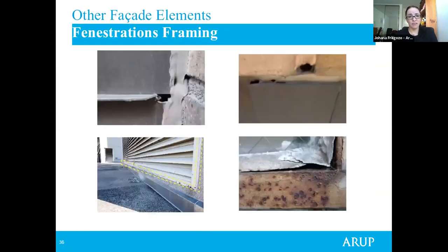Just some other defects on fenestration framings. We usually see a lot of gaps, especially with metal to metal elements. We see discontinuous application of sealant joints at interfaces between different types of materials. Sometimes there's splitting in the sealant, which is particularly common on louvers when the louvers are smaller than the opening in the facade main material, and therefore there's an inadequate width to depth joint or detailing, or the use of inadequate types of sealants. And in this photo, we can see some dried caulking. This is mainly due to aging, and sometimes there's debonding when the frame materials are corroding.